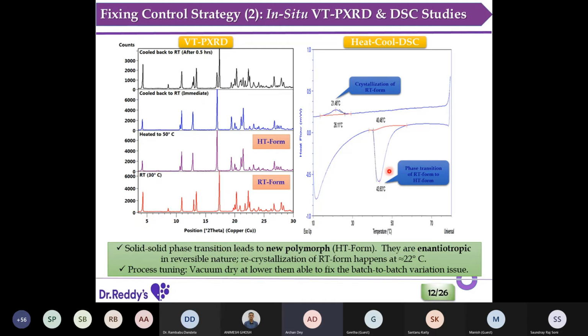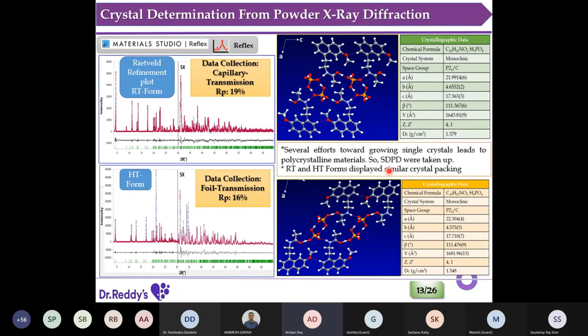And further, whatever study we did was not from process control and all these things. It's from scientific curiosity, and to get much more detailed understanding of the molecular level structure. So all we know, to get a molecular level structure we have to have a crystal structure. We made several trials to grow the single crystal, but we were never able to do that. Then we decided that we can solve the crystal structure from powder XRD. We made an attempt. The low temperature, so room temperature form, data was collected in capillary transmission, and the high temperature form was collected in foil transmission.